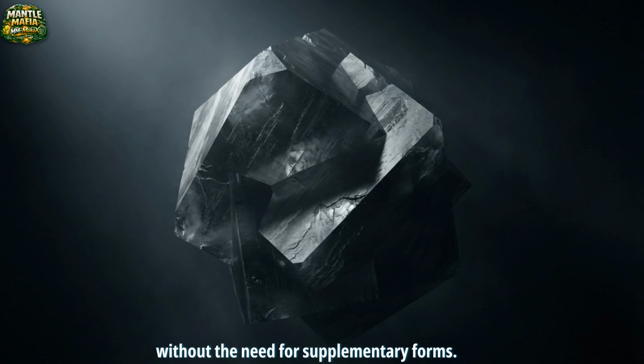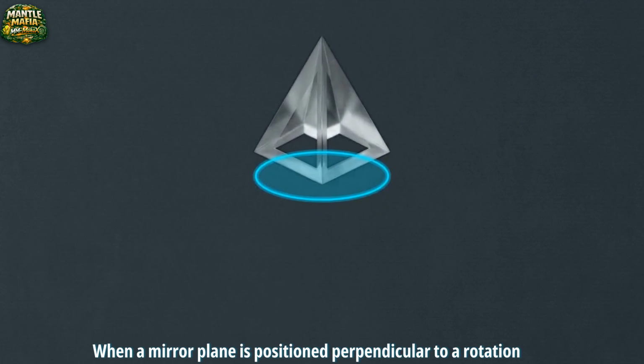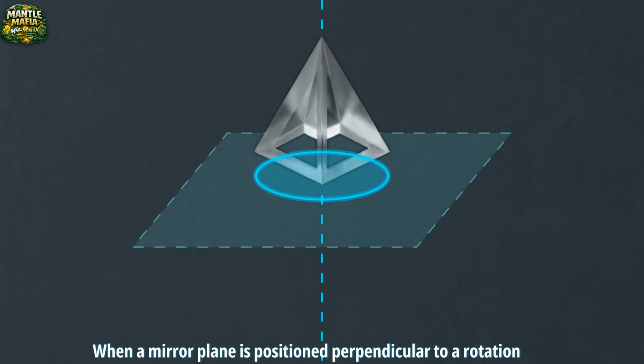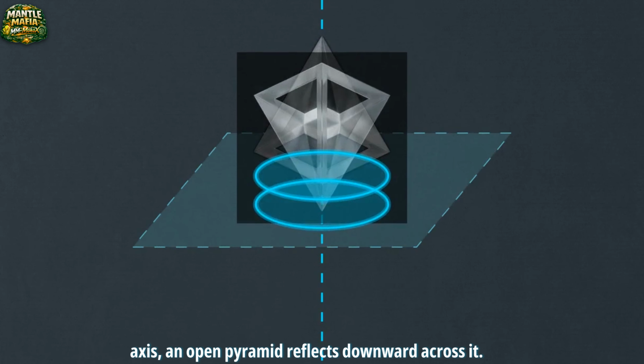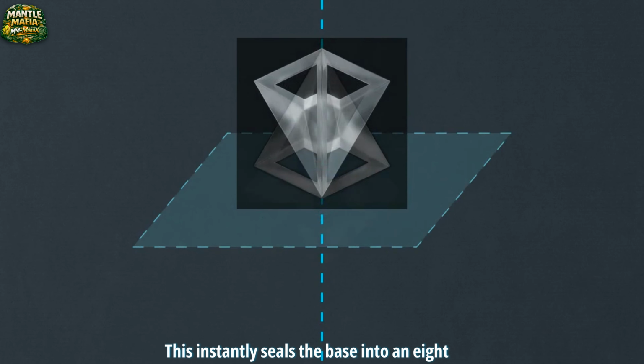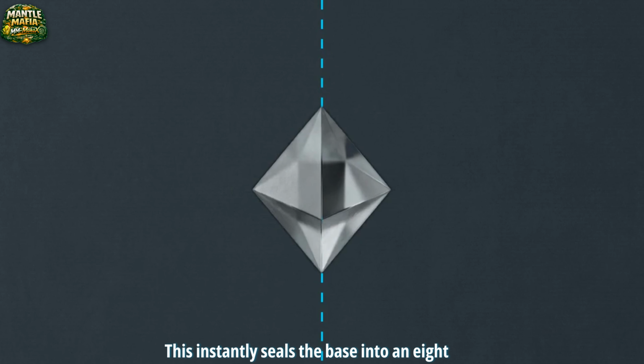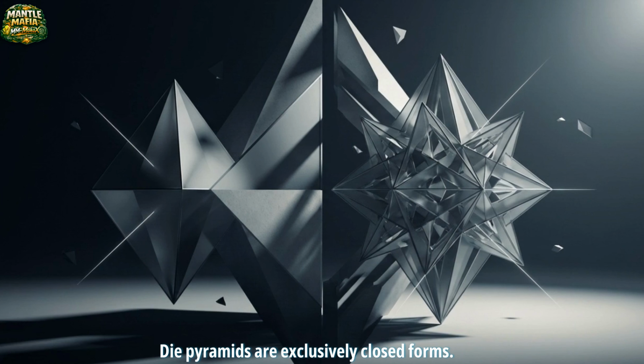Closed forms are self-sufficient sets of faces that isolate a volume of space without the need for supplementary forms. When a mirror plane is positioned perpendicular to a rotation axis, an open pyramid reflects downward across it. This instantly seals the base into an 8-faced tetragonal dipyramid. Dipyramids are exclusively closed forms. Depending on their axial symmetry, they generate between 6 and 24 symmetrical faces.